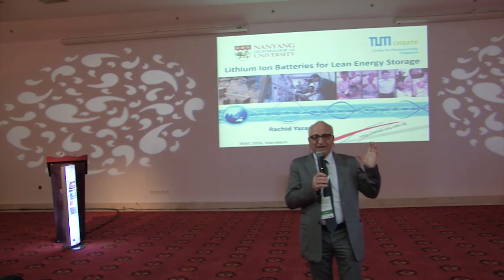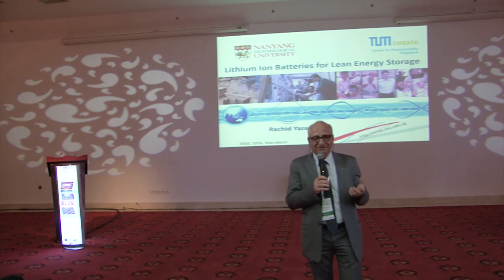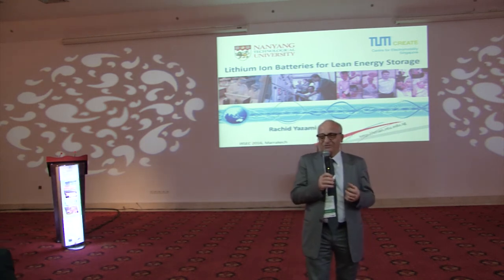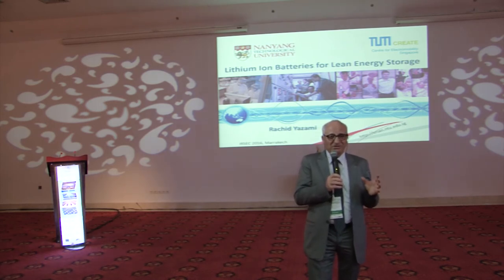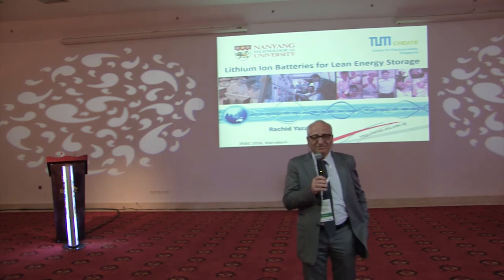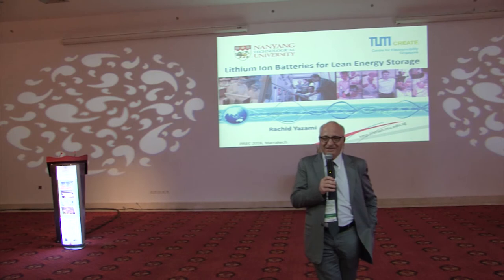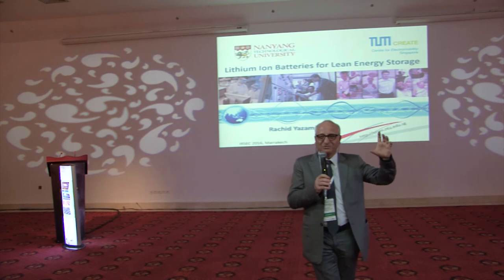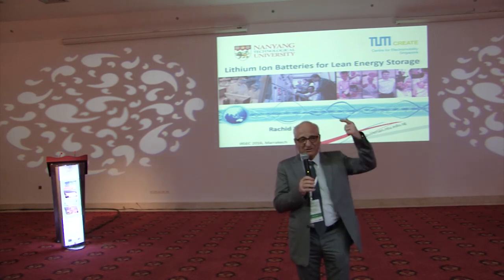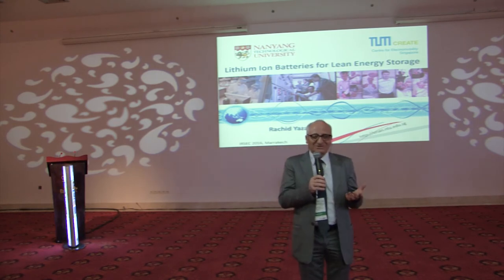Going from 90 to 250 Wh/kg was tremendous work done by academia — people in universities and national labs — and also by industry. Because of competition, if you have a battery that gives 10% more energy, you win market share. Sony's original concern in 1990 was safety first, but because of the race to increase energy density, even Sony started to use graphite instead of hard carbon as the anode — which was actually my own contribution to this field.